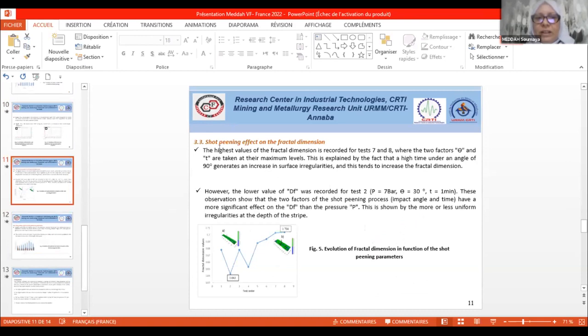And concerning the shot peening effect on the fractal dimension, the highest value of the fractal dimension is recorded for test number 7 and 8, where the two factors theta and t are taken at their maximum levels. This is explained by the fact that the high time and an angle of 90 degrees generate an increase in surface irregularity, and this tends to increase the fractal dimension.